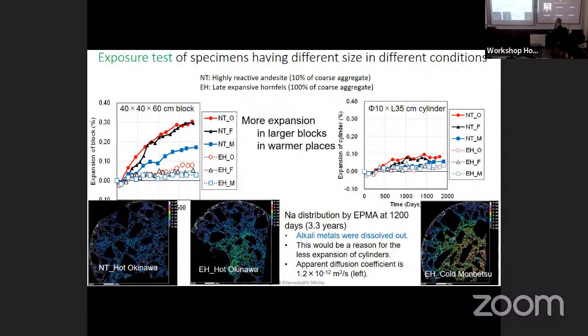There is one possibility. That's alkali leaching. In this case, we exposed two size specimens. One is this 40 by 40 by 60 centimeter block, like this. And another is a 10 centimeter cylinder. So expansion was completely different. Less expansion in the smaller cylinder. This kind of behavior has been explained by alkali leaching from the concrete specimen.